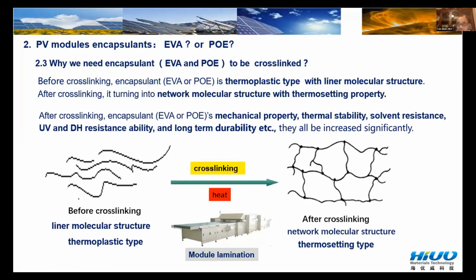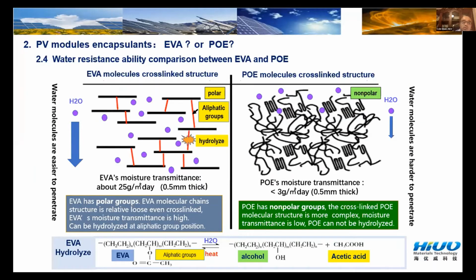Okay. Now let's look at the water resistance ability compared between the EVA and the polyolefin. The EVA molecular cross-linked structure is like this. EVA has polar groups. The EVA's molecular chain structure is relatively loose, even cross-linked. And EVA's moisture transmittance is high. You can see here it is about 25 grams per square meter per day. We calculate on a 0.5 millimeter thick film, okay?